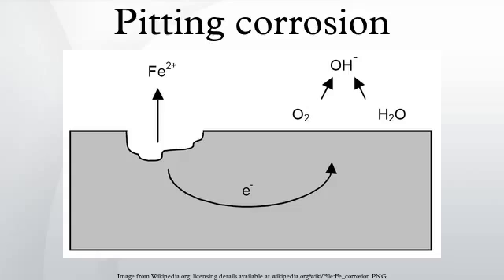A good example of the importance of environment/alloy combinations is carbon steel. In environments where the pH is less than 10, carbon steel does not form a passivating oxide film and the addition of chloride results in uniform attack over the entire surface. However, at pH greater than 10 the oxide is very protecting and the addition of chloride results in pitting corrosion.